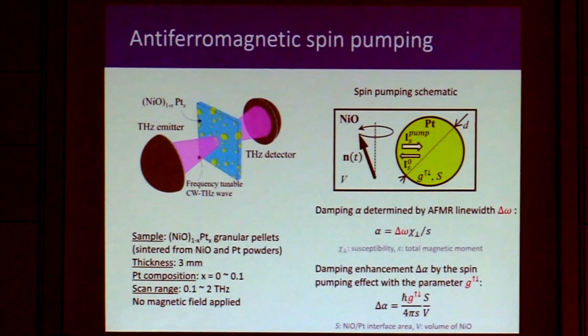Yeah, actually, first of all, I'd say it's not a usual combination, platinum and nickel oxide. But considering the spin pumping process, it seems to me that there is actually no net spin pumping going on, right? Because in ferromagnets, for spin pumping, we use linearly polarized microwaves, which do not really push any angular momentum into the system. That is because we're using a magnetic field to keep the orientation always there, so you have a continuous spin pumping out of the ferromagnet. But here in an antiferromagnet, there is no external field, right? There's an anisotropy field that gives rise to the resonance frequency. So maybe it's not net spin pumping, but a spin pumping from the two individual sublattices, the same, so eventually the spin current is cancelled.